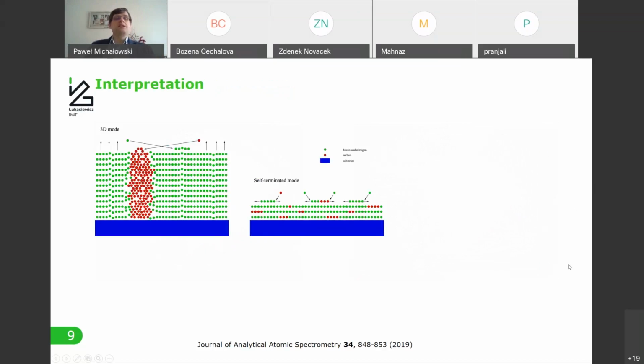Basically, in this three-dimensional mode, for the low reactor pressure, the average diffusion length of precursors of either boron or nitrogen or carbon is long enough so they can always attach to a preferred site. So whenever the reaction takes place, they will simply find a suitable location to get attached to. However, in the self-terminated mode for high reactor pressure, this is not the case anymore, and the average diffusion length is severely limited, and thus the atoms have to get attached to the growing film wherever the reaction took place. So that is why there is absolutely no correlation of the position of carbon precipitates.